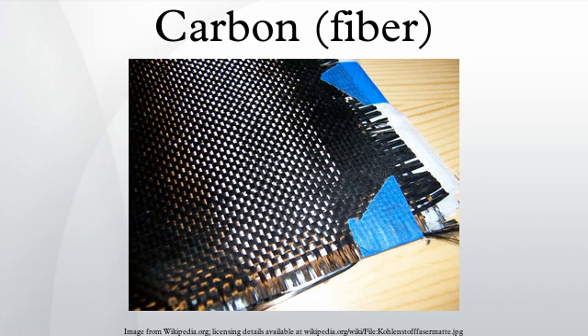Since the late 1970s, further types of carbon fiber yarn entered the global market, offering higher tensile strength and higher elastic modulus. For example, T400 from Toray with a tensile strength of 4000 MPa and M40, a modulus of 400 GPa. Intermediate carbon fibers, such as IM600 from Toho Rayon with up to 6000 MPa were developed. Carbon fibers from Toray, Celanese and Akzo found their way to aerospace application from secondary to primary parts, first in military and later in civil aircraft as in McDonnell Douglas, Boeing and Airbus planes. By 2000 the industrial applications for highly sophisticated machine parts in Middle Europe was becoming more important.